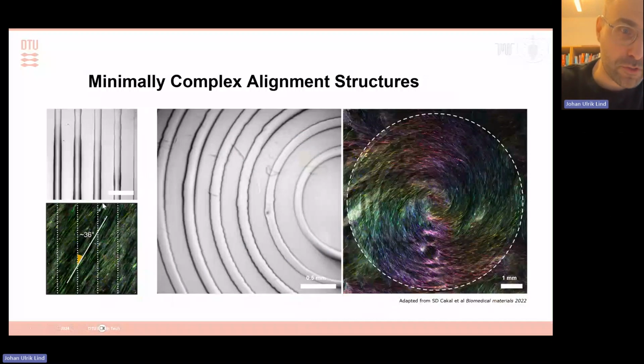Okay, so what we observed was that while we can get very nicely aligned myotubes using these crude patterns, we always observed that these come at an angle, and this was extremely robust. So that means that if you print circles, a circular pattern, then you actually end up with a spiral. So this is just color-coded for orientation here. But you can appreciate that the myotubes actually follow a spiral, even though the print is a circle. So it looks beautiful, but we would like to be able to have a much tighter control of the organization.